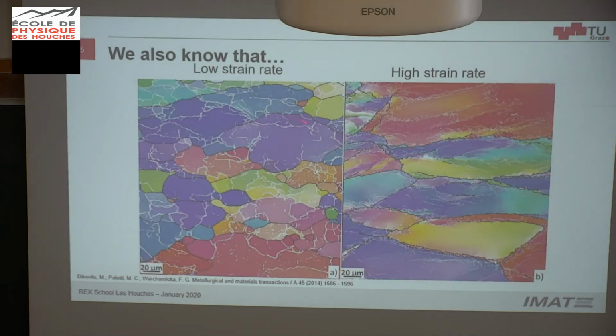We also know from other alloys where we don't have this martensitic transformation, so we can watch what happens in EBSD in the beta phase. We have the high angle grain boundaries in black and the low angle grain boundaries in white, and we see substructure formation. If we increase the strain rate, we also see substructure formation in a very heterogeneous way. This makes the processing of this material very complex.